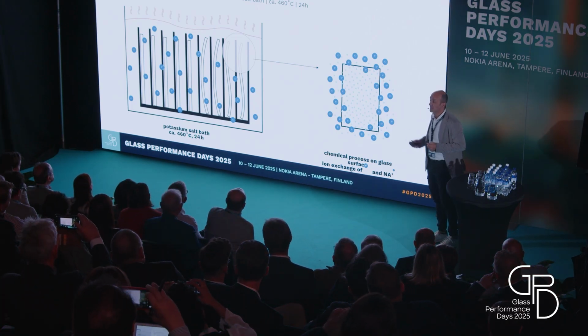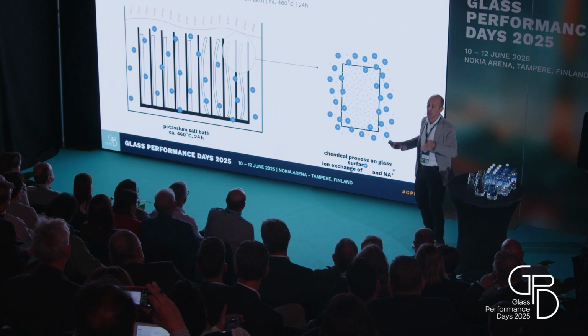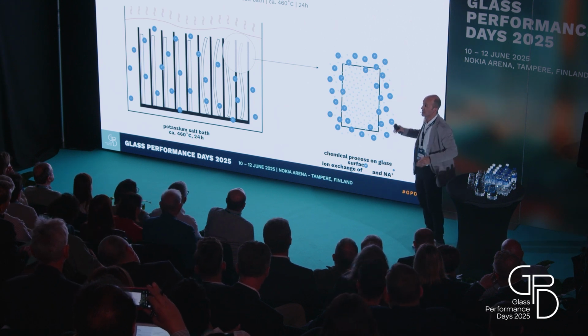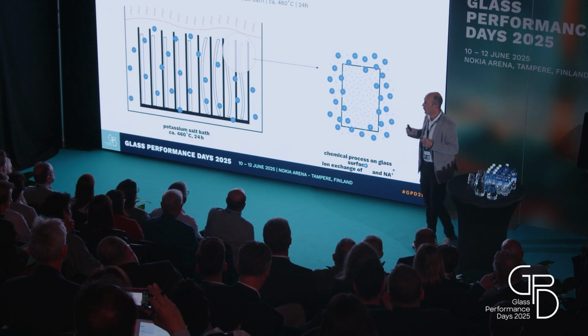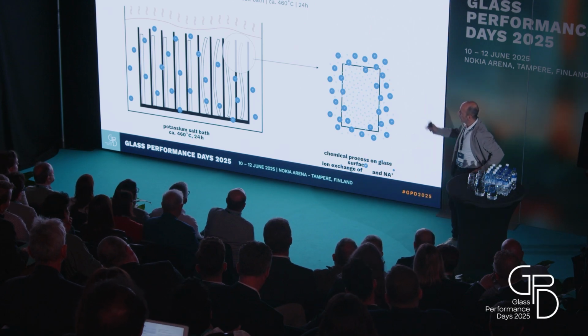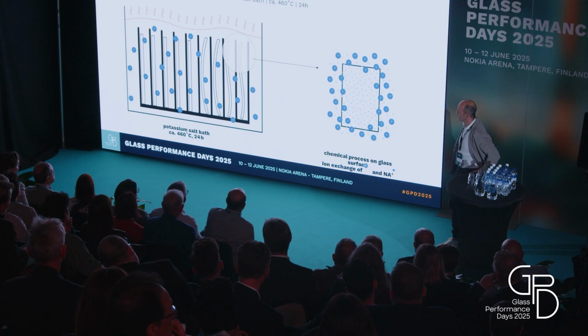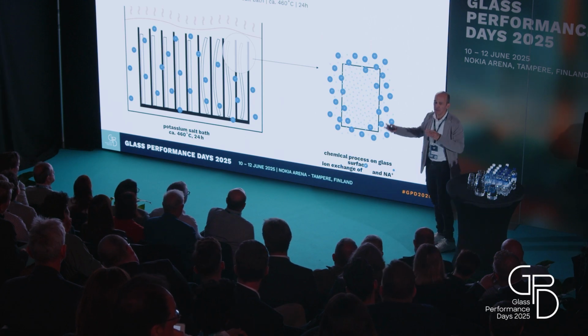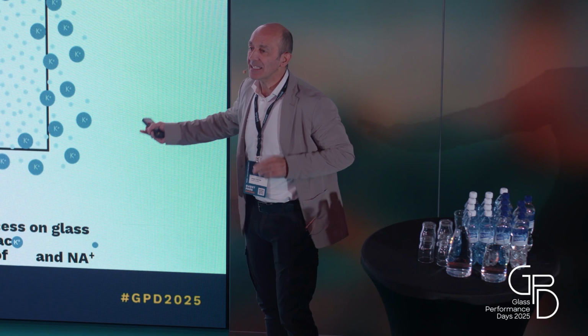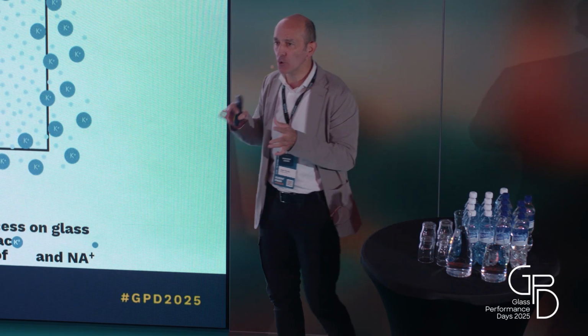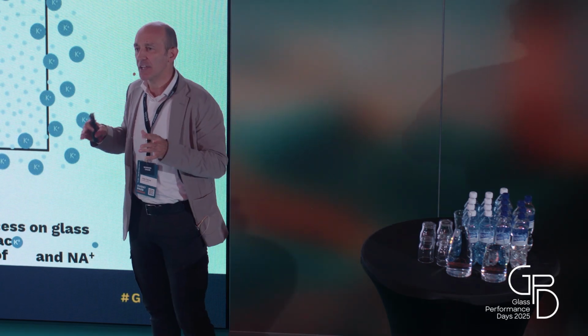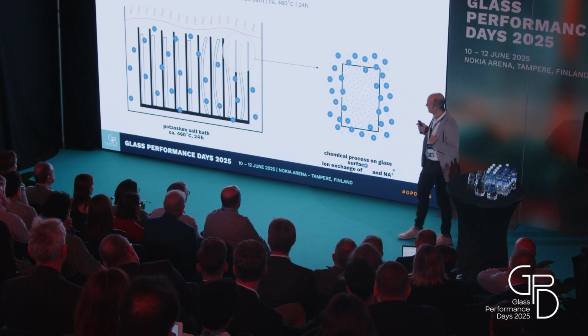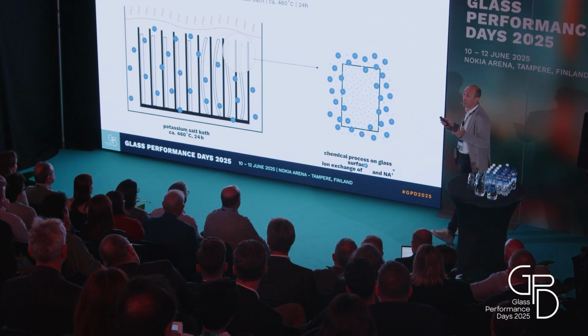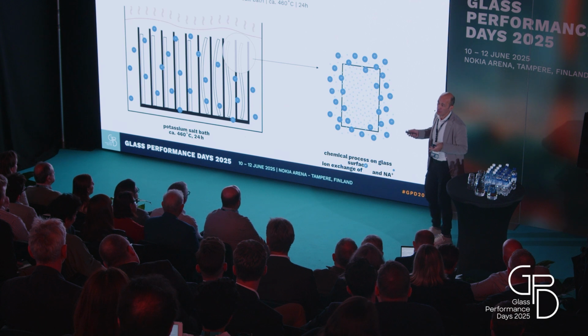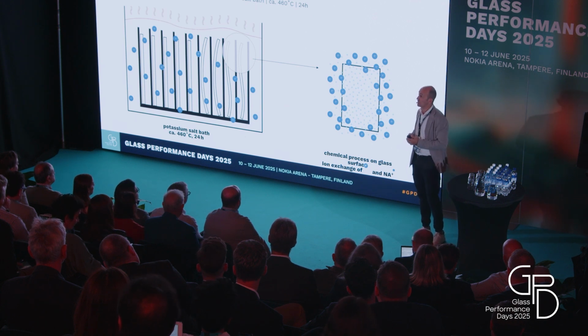The process, probably you know, basically consists in putting the glass, any sort of geometry, from a flat piece of glass to a very complicated geometry that we have previously slumped over a mold. We put that in a bath at approximately 460 degrees centigrade for 24 hours. I mean, the time depends on what we want to do. And there's an ion exchange of smaller sodium ions on the glass surface, exchanged by bigger potassium ions. So with this technique, we can easily reach around 380 megapascals of surface compression with soda lime glass.